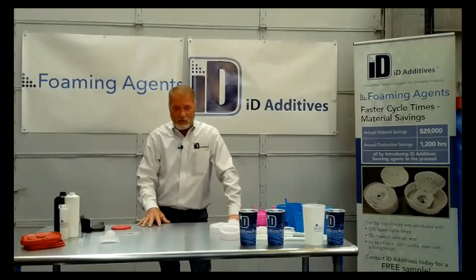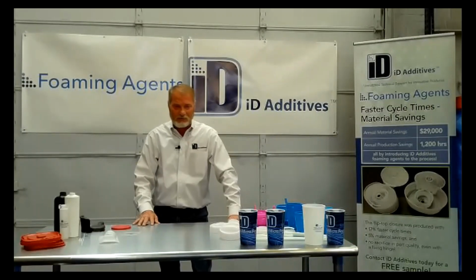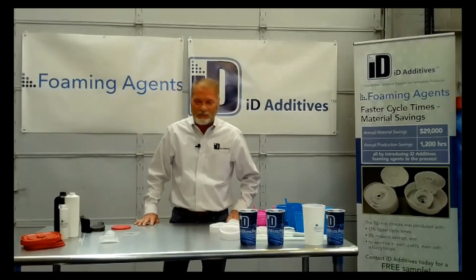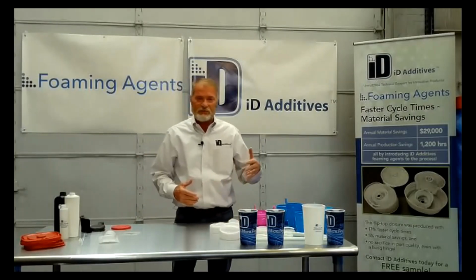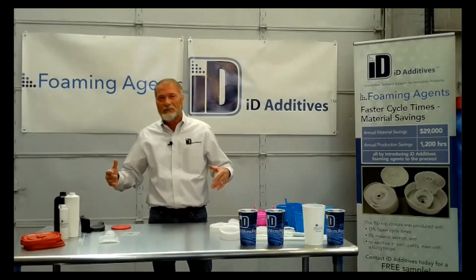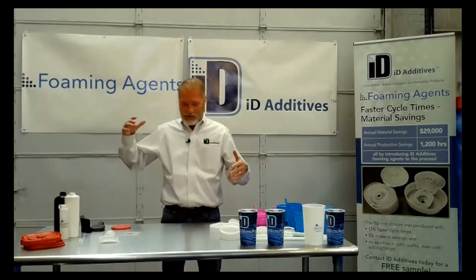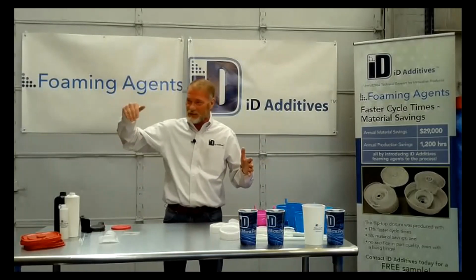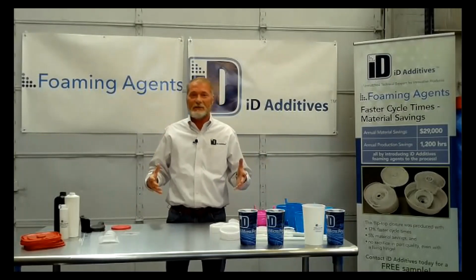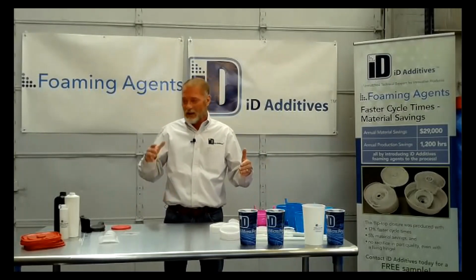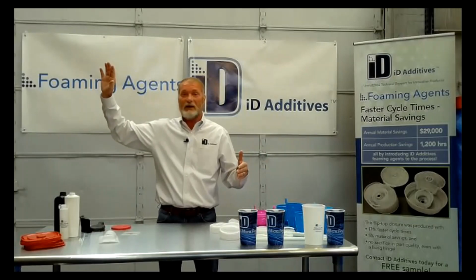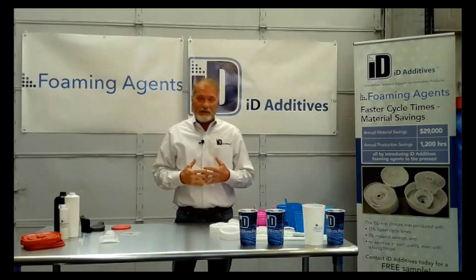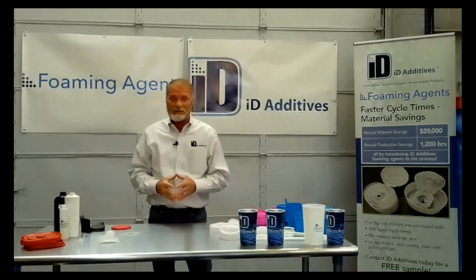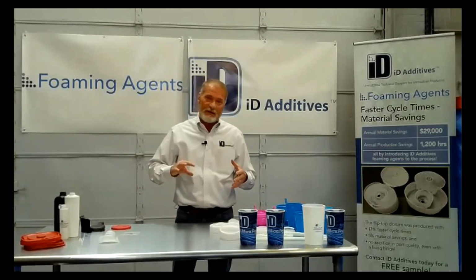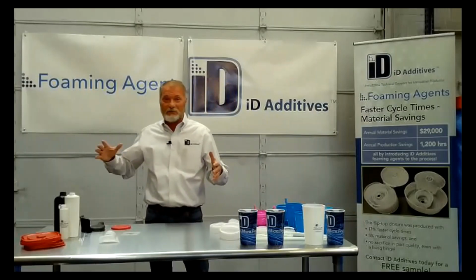So that's injection molding. I want to talk a little bit about residence time when it comes to injection molding. Some people choose screw delay and then zip it back. But what happens is as you delay it forward, material drops on the screw, it sits there for your delay time. And that gas is going right up out the hopper. So I recommend that you only use enough time to freeze the gate off, and then turn your RPM down to where it gets back just before the mold opens.